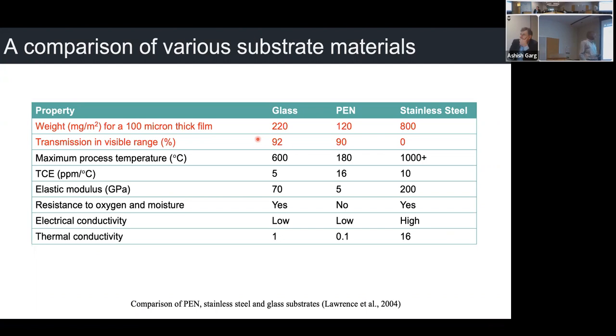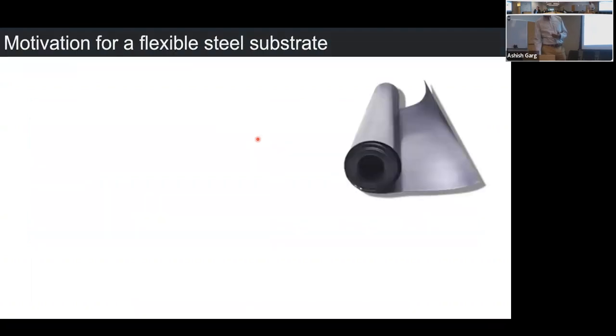Steel also has a comparative coefficient of thermal expansion. It has a very high elastic modulus. It could be resistant to oxygen and moisture depending upon the composition, and it has high electrical conductivity and high thermal conductivity. The bad thing about steel is that its weight is on the higher side and it doesn't transmit any light. This is the major problem. The latter is the major problem, because weight is not too high when you compare a very thin film of steel, but the transmittivity is zero. So what do you do? Where do you get the light from? So this was a major challenge in going about this project.